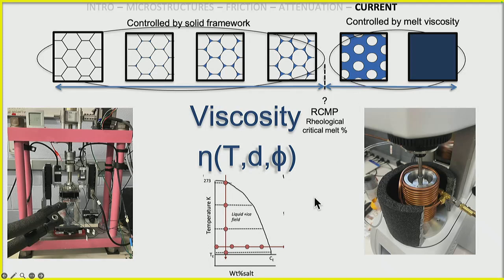Just as an aside, our plan of attack is kind of twofold, where you can control partial melt by either staying at a constant temperature and then little by little adding more salt in each sample, or you can do it by a single composition and then just changing your temperature, and then by your lever rule you'll be changing the fraction of melt. This is more like what a moon would be feeling, right? Where it has a certain dilute composition and there'll be a temperature variation in the shell. However, maybe we'd be confused by the temperature effect on the ice as opposed to the system effect. So we're going to attack it in both ways, and that's what she's been working on.